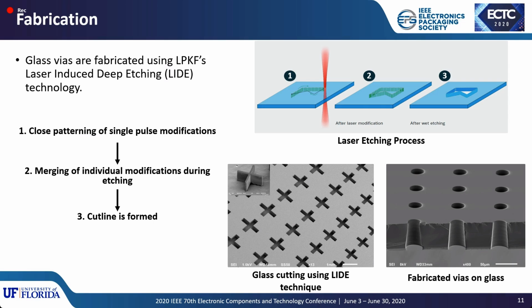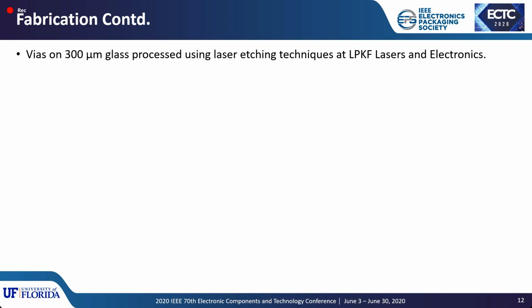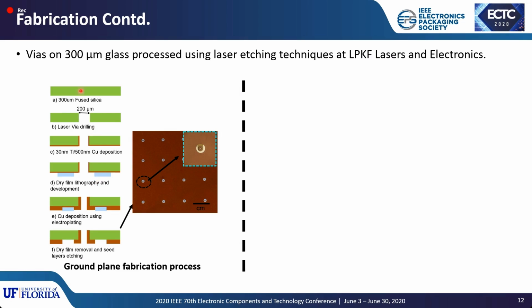Once the vias are fabricated, the remaining steps of the fabrication are divided into two processes. The first one is the ground plane fabrication. As you can see, once the vias are fabricated, we deposit 30 nanometers of Ti followed by 500 nanometers of copper using a sputtering technique.